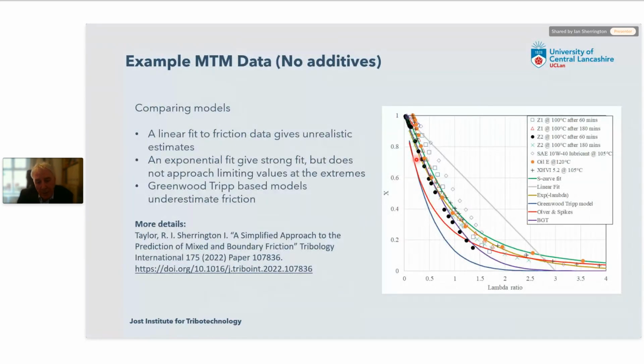If we compare the friction coefficient prediction, or let's say the degree of mixed and boundary lubrication, with the lambda ratio for a range of different models, we see something interesting. So here's the green line, which is our model here. And if I take, for example, the Greenwood and Tripp model, which is probably one of the most commonly used models, you can see there's a significant difference between the two models.